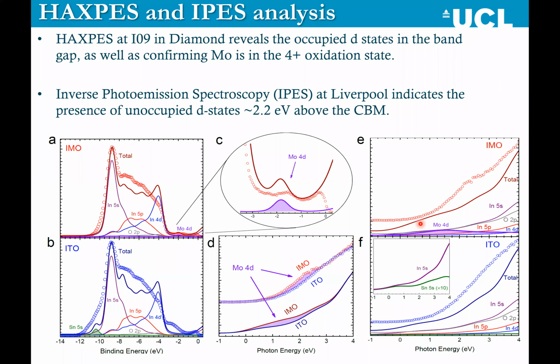We used inverse photoemission spectroscopy done by Tim Veal's group at Liverpool to find the presence of the unoccupied D states about 2.2 electron volts above the bottom of the conduction band. And we also used some XAS and XES measurements done by Professor Louis Piper from the University of Warwick, who at the time was at Binghamton in the US, and I think he went to the Advanced Light Source in America to do these experiments, also showing these unoccupied states 2.2 eV above the bottom of the conduction band. So we have now the spectroscopic evidence that our model was correct and that we understood the behavior of molybdenum in these systems.